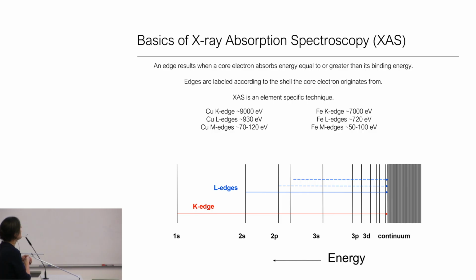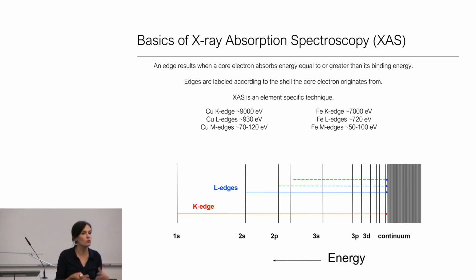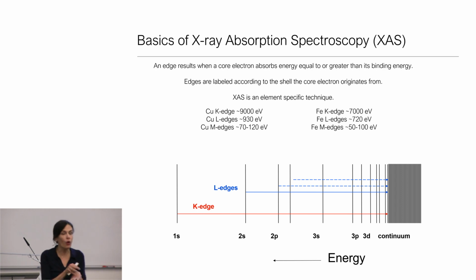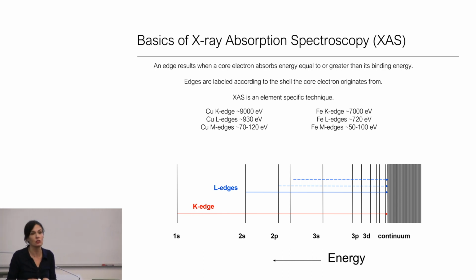Now what you see as we move down in energy, the L edges, these refer to ionizations from the 2s and 2p levels. You can see these take about an order of magnitude less energy, so they're around 900 or 700 eV. They fall into what we often refer to as the soft X-ray regime, and you can see their energies are getting closer. As we go even further out towards the valence, to the M edges, from the 3s, 3p, and 3d levels, you can see that even copper and iron start to have overlapping energies. This is also what you see in valence photoemission. This is what we as spectroscopists sometimes refer to as spectral congestion: the idea that you have overlapping features that make unique identification more challenging.